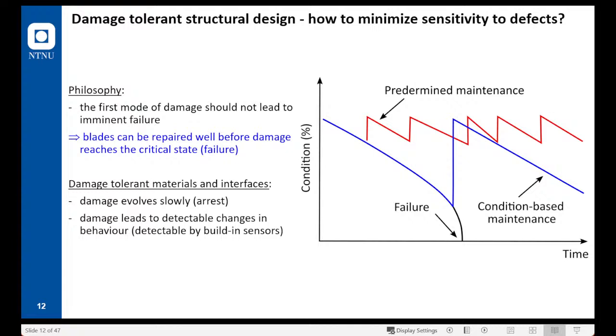Now, as we move to longer blades, it's very important to introduce the concept of damage tolerance or damage tolerant structural design. That means that our blade should be insensitive to defects, or in other words, the first mode of damage should not lead to failure of the component. And secondly, we have to develop damage-tolerant materials and interfaces. That means the damage should evolve slowly, or sometimes even stop to grow. But it's also important that the damage grows to a size that can be detected by non-destructive techniques. That's the only way that we can understand that our blade is being damaged at some location.